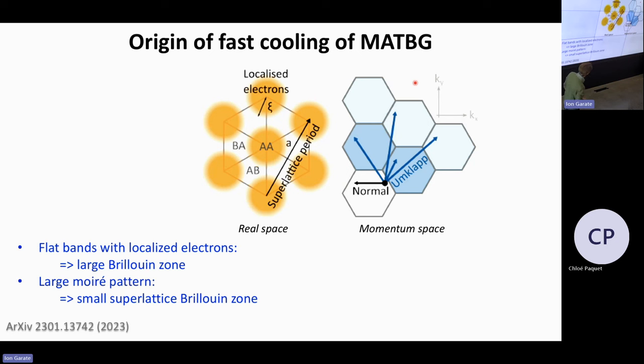But there's a trick that nature kind of invented for us in this system, and that is umklapp scattering. So this is very well known for phonons. So with phonons at room temperature, umklapp scattering is dominating the scattering of phonons. So it's a process where you scatter out of the Brillouin zone and you fold back into its own Brillouin zone. This is how you lose momentum. Now, this has also been observed at very low temperature between electrons. So electron-electron umklapp scattering. And as far as we know, this is the first observation of an electron-phonon umklapp scattering process, where an electron couples to a phonon by folding out and back out of the Brillouin zone.